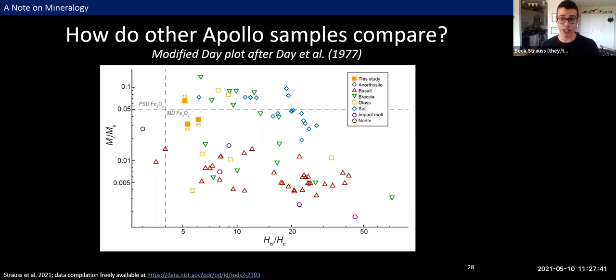What I'm showing here is a Day plot, and these are typically used to understand how hysteresis parameters of different samples compare to each other. On the x-axis, we have remanent coercivity divided by coercive force, and on the y-axis, we have saturation remanent magnetization divided by saturation magnetization. And all of that aside, the hope with a Day plot is that samples with better recording properties should plot toward the upper left, and that should correspond with better magnetic fidelity. So what we've built is, to our knowledge, the largest published compilation of hysteresis parameters from Apollo samples to date. Each data point that you're seeing here represents one sample or subsample from the literature, sorted by bulk rock type as kind of a first pass, and the data from our study is shown in orange squares up here.